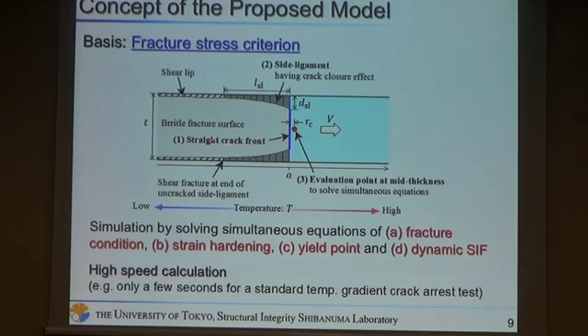First is the shape of crack front is straight. Second is the side ligament has a crack closure effect. The third is the evaluation point is only at the mid thickness. And the brittle crack propagation and arrest behavior is simulated by solving the simultaneous equations of fracture condition, strain hardening, yield point, and dynamic stress intensity factor. One of the features of the model is high-speed calculation. For example, it takes only a few seconds for a standard temperature gradient type crack arrest test.